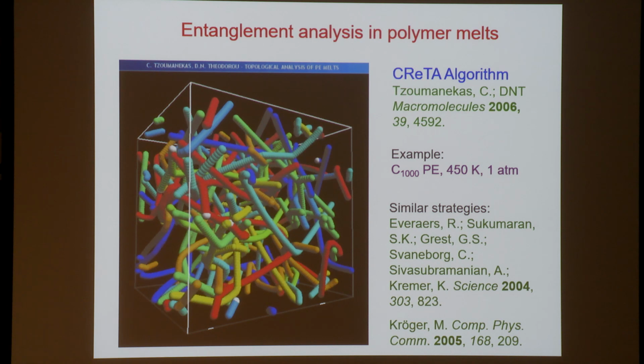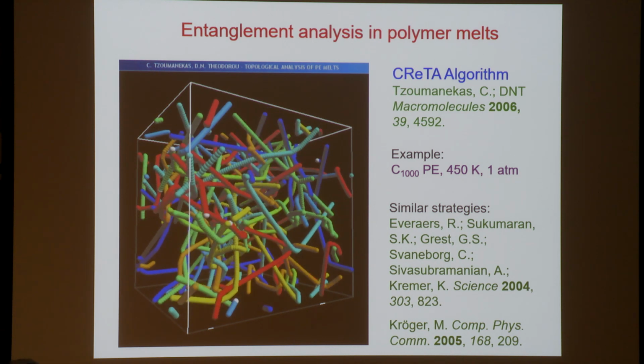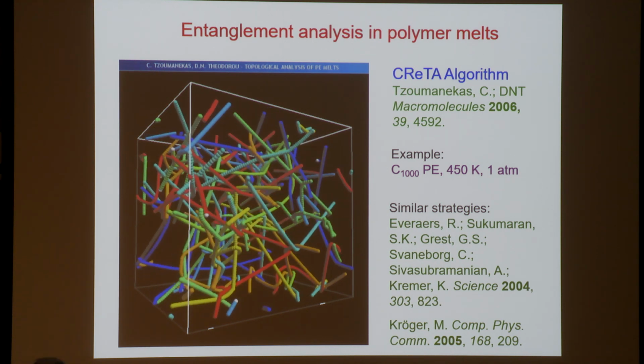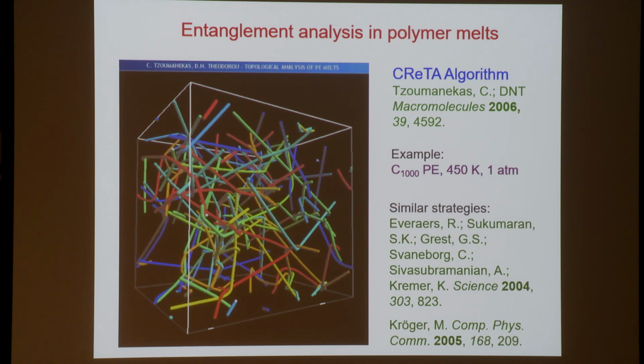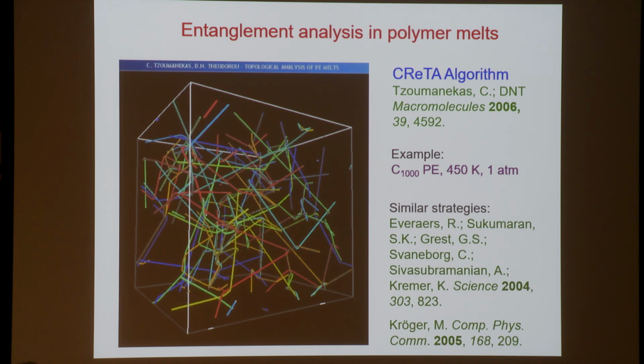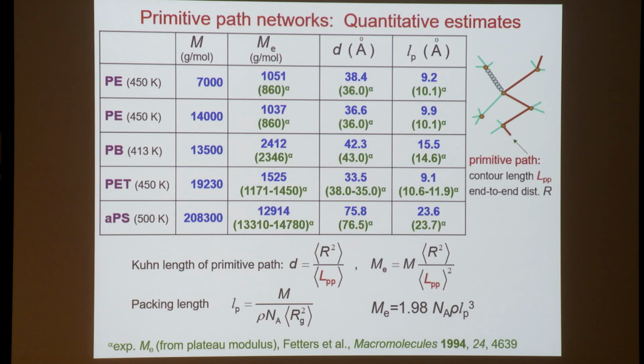So during the ultimate stages of this reduction process, you see that from the initial atomistic system, one gets a set of zigzag lines coming together at topological constraints of coordination number 4. So these zigzag lines are our picture of the so-called primitive paths of the chains, a term coined by Sam Edwards, and the topological constraints are our picture of entanglements. So one can go into the reduced structure and analyze the statistics of these entanglements.